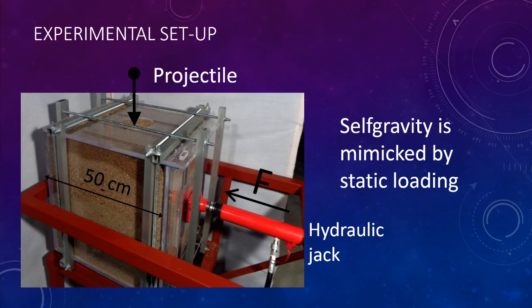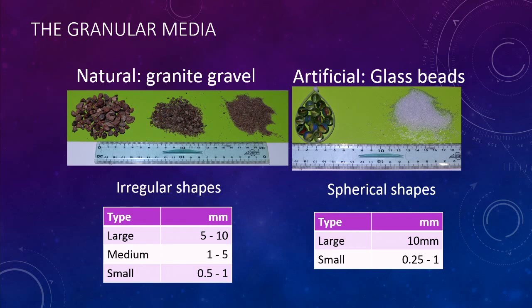What we have done is to build an acrylic box filled with different types of granular media. Then we shoot a projectile, and in order to simulate the self-gravity, we introduce static loading through a hydraulic jack in order to increase the pressure inside the box. The kind of material that we have used is natural material like granite gravel, or artificial glass beads, either these very small ones, or the ones that we used during our childhood.